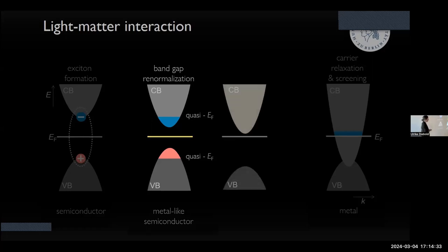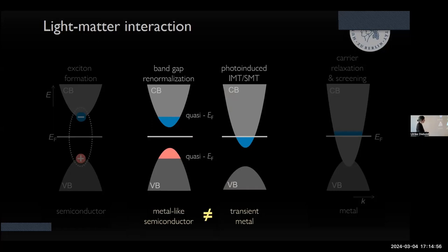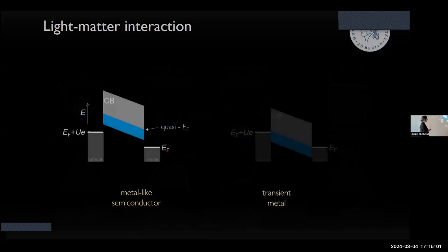But you can drive a system optically so strongly, and different mechanisms can play a role, that one of the bands crosses the equilibrium Fermi energy. Then we also have free carriers, but they are at the equilibrium Fermi energy. And then, and only then, we can speak of a transient metal. I'm emphasizing this difference so much because this is very often mixed up in some communities, and it makes a huge difference when you think about applications.